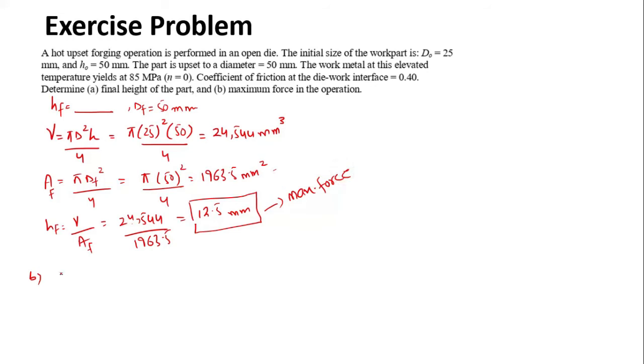Right. So we will find out the strain at this height, that is equal to ln of h naught by hf. We have h naught equals 50 divided by 12.5. So the strain would be equal to 1.3863. So based on the strain, we will find out the flow curve, the flow stress.